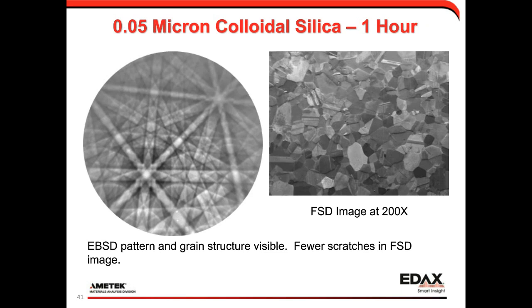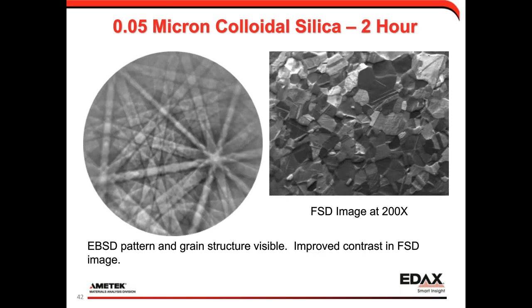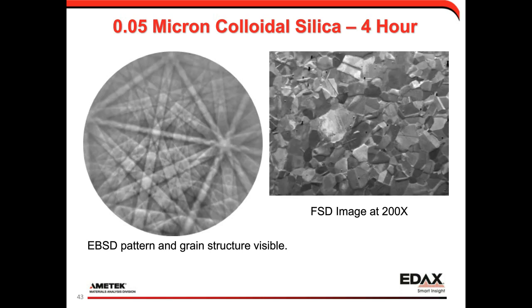This is now 1 hour of colloidal silica. You really see fewer scratches now. We're kind of removing that final bit of deformation. This is now at 2 hours. You can see we get pretty strong contrast. We are also starting to get a little bit of topography. You see some of the grains are a little more recessed relative to some of the other ones. And this is after 4 hours of colloidal silica polishing. In this case, we'd say it looks like it's a pretty pristine surface for EBSD.